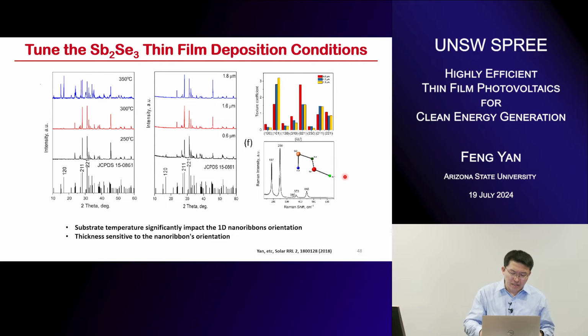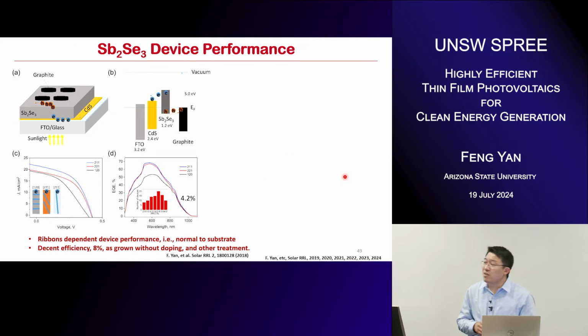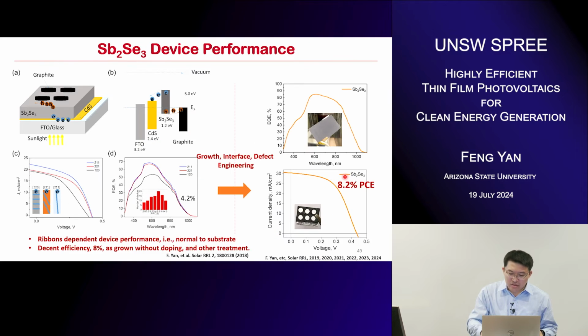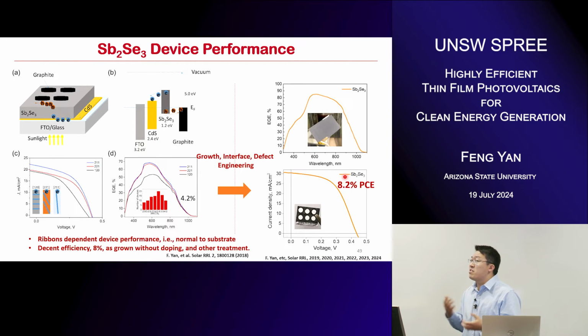And particularly, this needs a lot of work, and the screening process is pretty painful. But once you get a good quality film, and our initial film is very low efficiency, roughly 6 years ago, it's only around 4%. But gradually, if we further engineer the whole process, we can get around 8%. So imagine that this is just the pure film without any engineering yet.